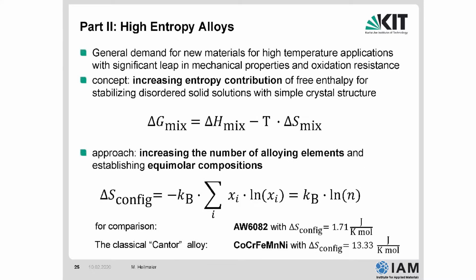Part 2, high entropy alloys. The concept, which is just a concept, this is not a theory, is very simple. The concept is that we get an increasing configurational entropy contribution to the free enthalpy, delta G, for stabilizing disordered solid solutions with simple crystal structures if we increase this mixing entropy. So this is a basic thermodynamic principle. Free enthalpy G is enthalpy H minus temperature times entropy S.